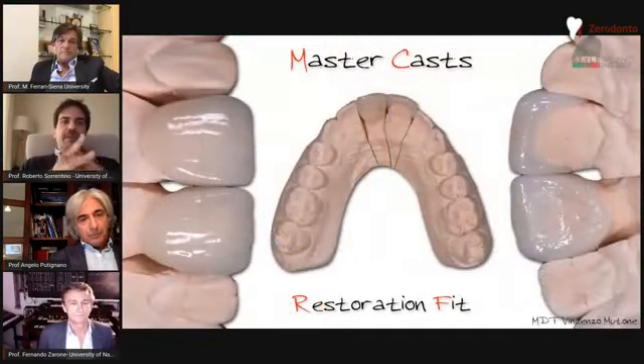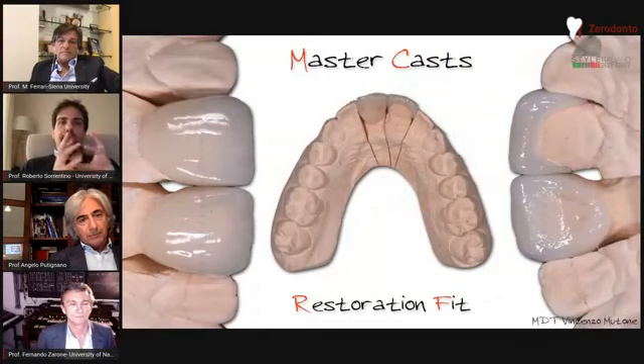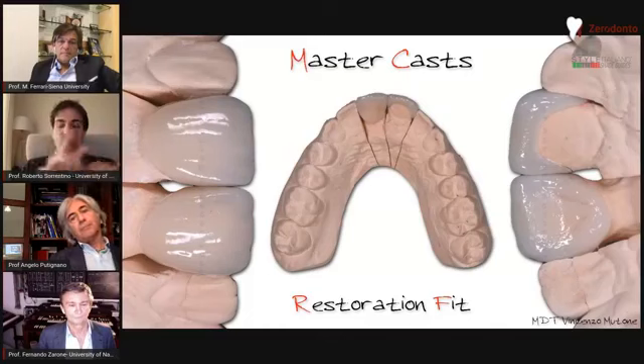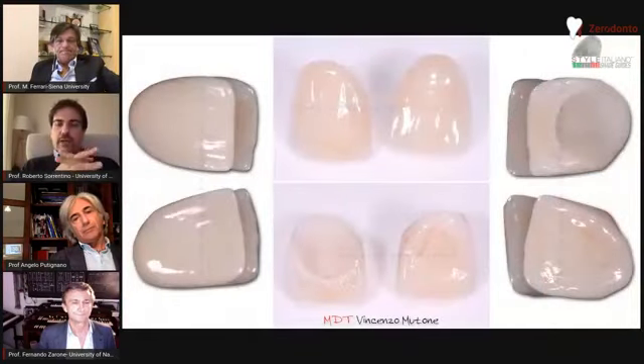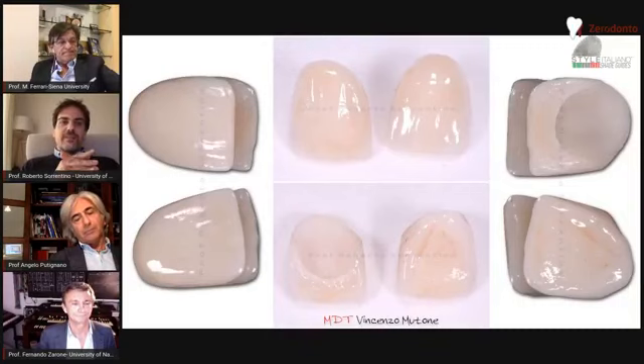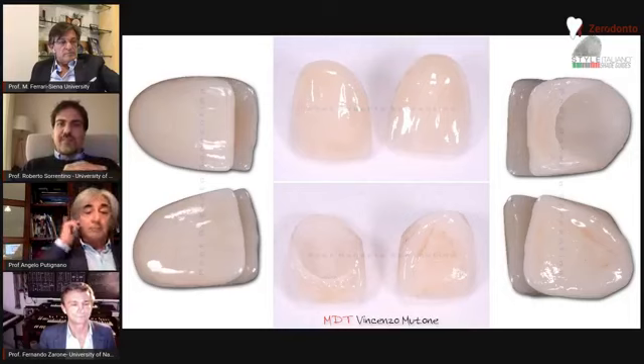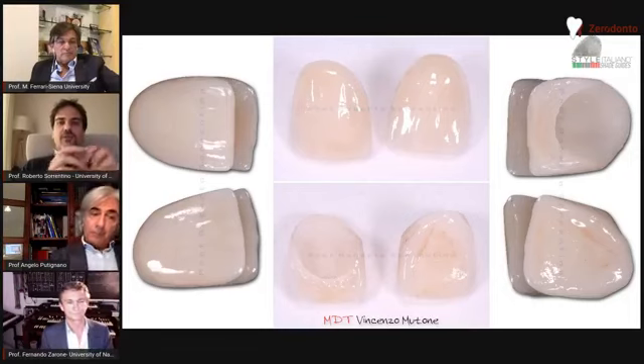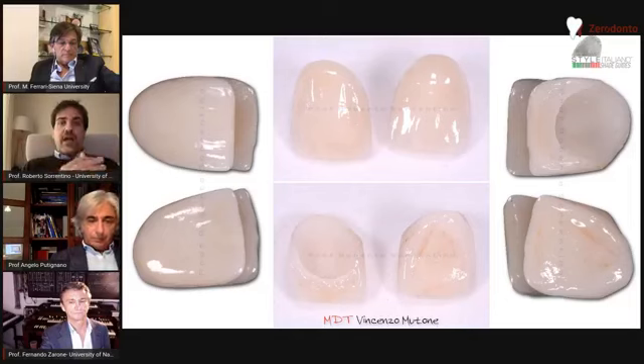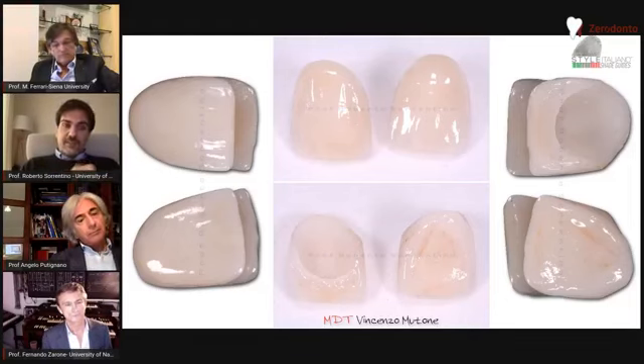And as you all know, this is not possible, for example, with feldspathic veneers. The details of the master cast show the optimal precision and marginal fit of the lithium disilicate restoration. These were pressed restorations fabricated by Mr. Vincenzo Mutone. And the crystalline properties of the material allow to extol the translucency and opalescence, achieving a very natural tooth-like appearance of the restorations, keeping at the same time excellent mechanical properties.